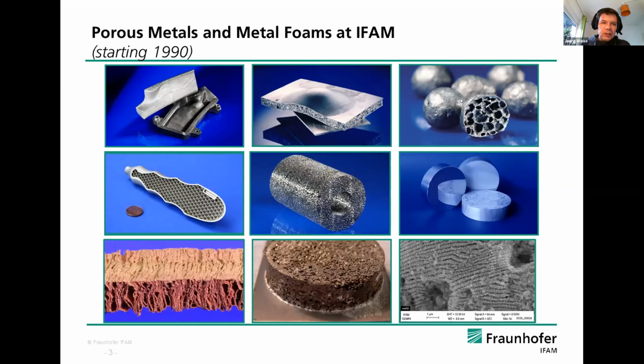Porous materials not only produced by classical foaming, but also by other techniques like, for instance, additive manufacturing, or like casting. In the middle, you see one example of an open porous aluminum foam, which was produced by means of infiltration of placeholder structures with aluminum melts. On the right side, you see some examples of, in this case, cast syntactic foams. I will show some examples later. And when you look at the bottom, we are also working on sintered fiber structures. In this case, it's hollow copper fibers sintered to a heat exchanger structure.